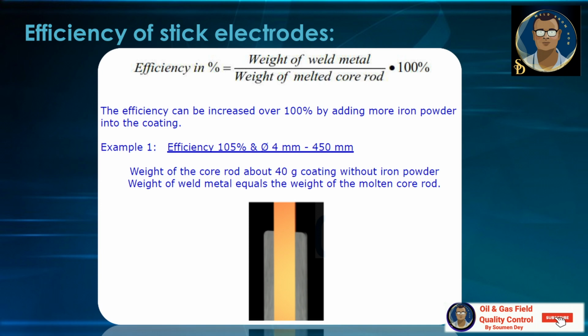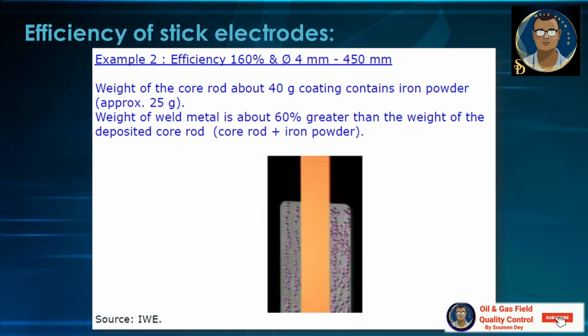Example 1, efficiency 105% for a 4mm, 450mm long electrode. Weight of the core rod is about 40 gram. Coating without iron powder. Weight of the weld metal equals the weight of the molten core rod. And in example 2, you can see the core rod is the same, 40 gram, which contains iron powder approximately 25 gram in the flux coating. Weight of the weld metal is about 60% greater than the weight of the deposited core rod. So here you get 160% deposition from a 450 millimeter electrode.